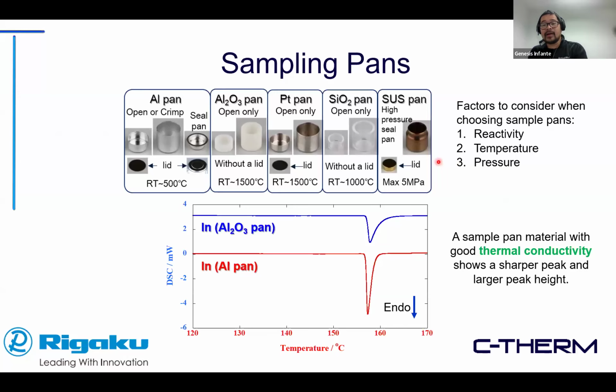A very important consideration when we're looking at the DSC is how we're going to handle the sampling itself. We can start with choosing the type of sampling pan or crucible that we're going to use to contain our samples. There are different types of pans available commercially. Typical pans could be aluminum, alumina, ceramics, platinum metal, glass, and stainless steel, for example. There are different factors that you have to consider, such as reactivity with your sample. You don't want your samples to be reacting actively with the pan that you're using, so you want to make sure that the pan and the samples are inert against each other. Another factor is the temperature range that you want to look into.